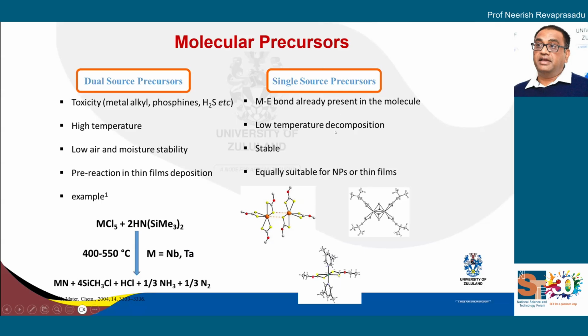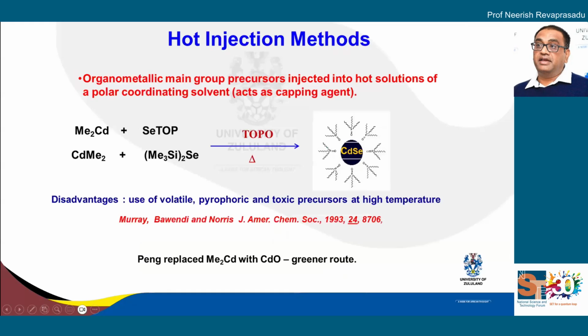We can overcome this by using a complex that already has both the metal and the chalcogenide. So the metal chalcogenide bond is already present in the molecule. The temperature of decomposition is much lower than for the dual source, and it's more stable, and it's more flexible.